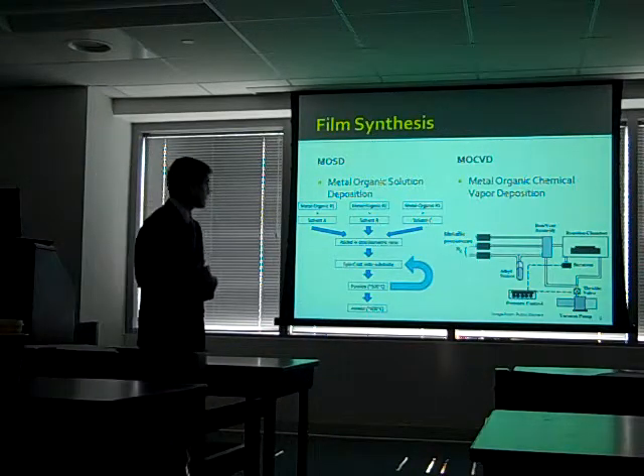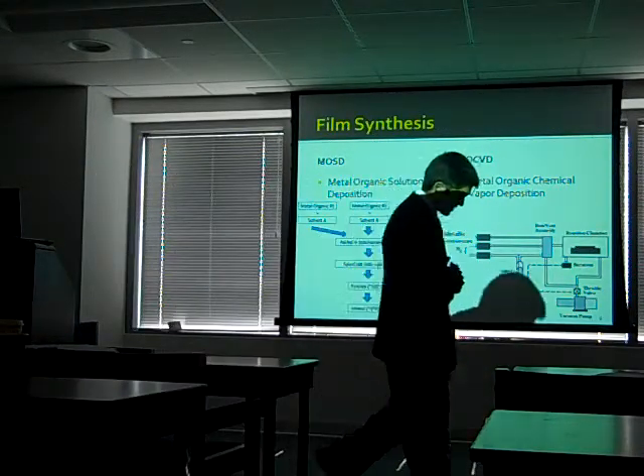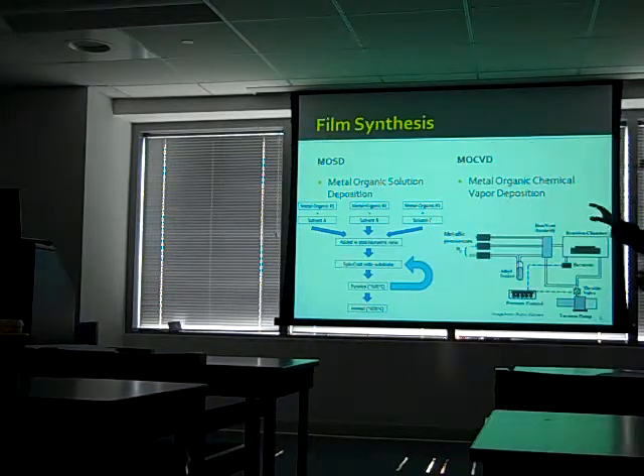about. BST thin films can be synthesized by a lot of different techniques, but the two that are important to understand for this work are metal organic solution deposition and metal organic chemical vapor deposition. The films produced in this study were made by the MOSD technique and are made by the dissolution of 3 metallic precursors: barium acetate, strontium acetate, and titanium isopropoxide.